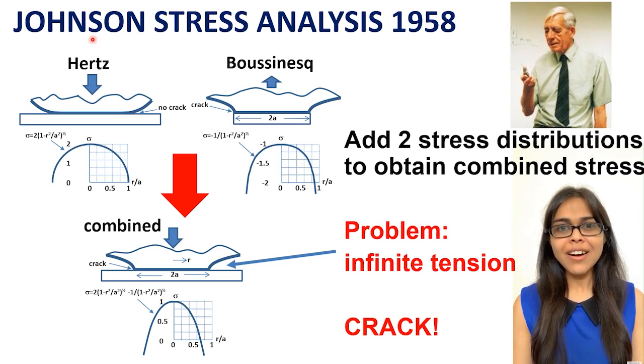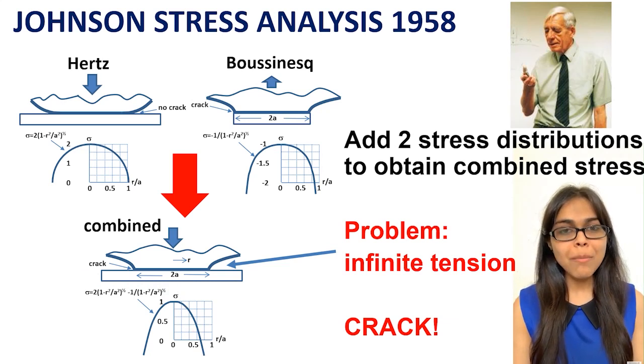This is the Hertz 1882 pressure distribution for zero adhesion. Here is the Boussinesq pressure distribution from 1885 for adhesion between a cylindrical punch and an elastic material. Johnson added these two stress distributions together and then observed the infinite stress at the edge of the combined contact, but failed to consider the Griffith energy argument to analyze the equilibrium. He presumed that the stress analysis was sufficient to solve the problem. No, it is not.